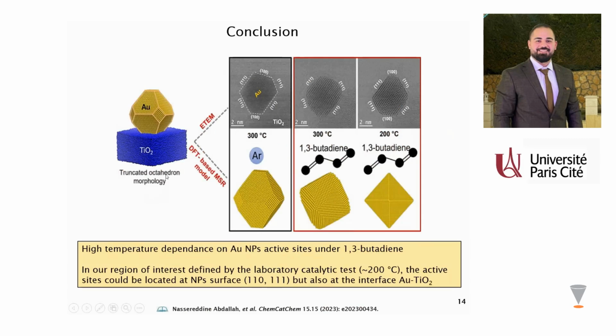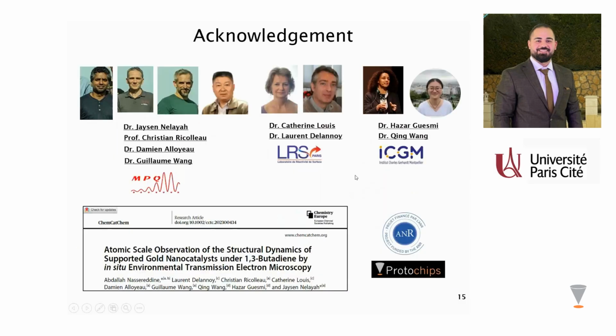Finally, in conclusion, by grouping the experimental ETEM observation and the theoretical DFT-based MSR model, we saw that the gold nanoparticle has a high temperature dependence concerning the active sites for butadiene adsorption. In our region of interest, defined of course by the laboratory catalytic test, around 200 degrees C, the active sites could be located at the nanoparticle surface, like 110 and 111 facets, but also at the interface between the gold particle and the TiO₂ support.